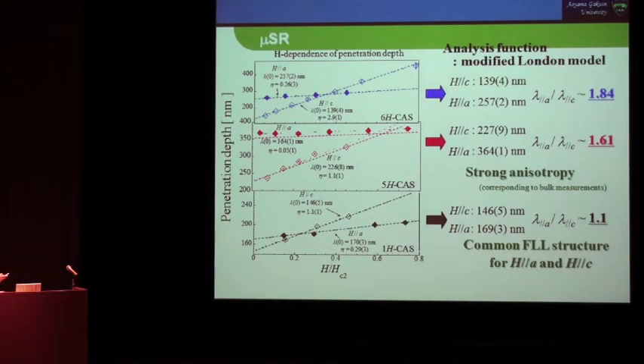Another method result is H dependence of the penetration depth. We use the modified London model, and lambda A over lambda C is 1.84. However, in this case at 1.61. However, in this 1H, lambda A over lambda C is almost unity. Big difference.